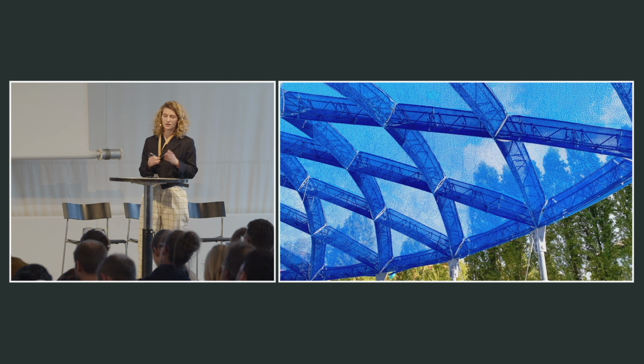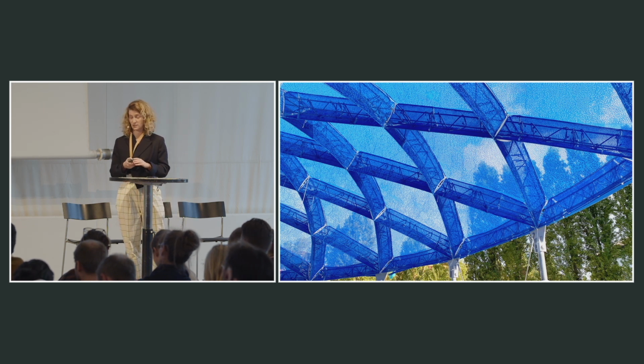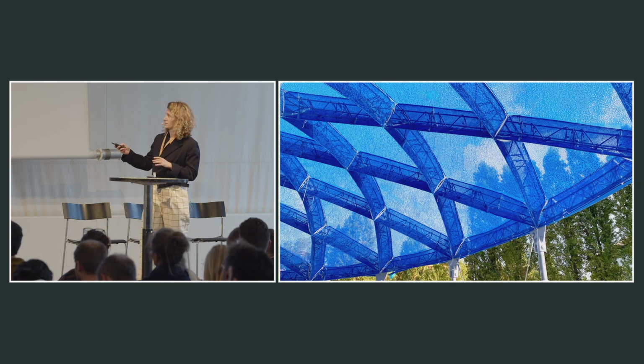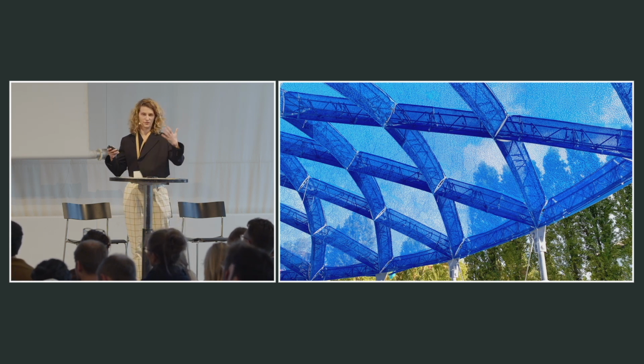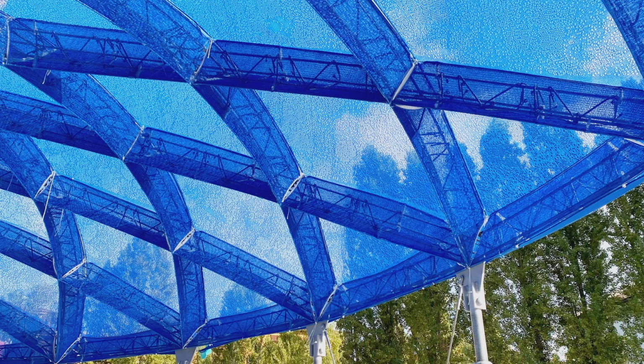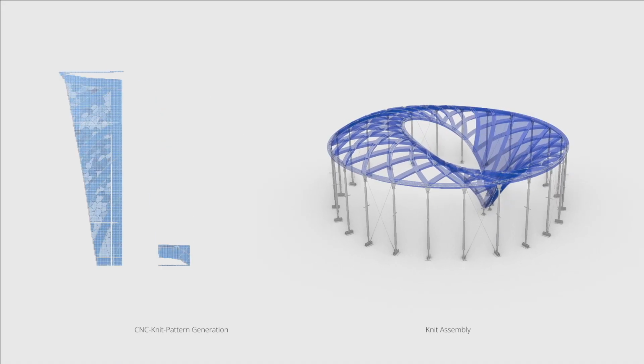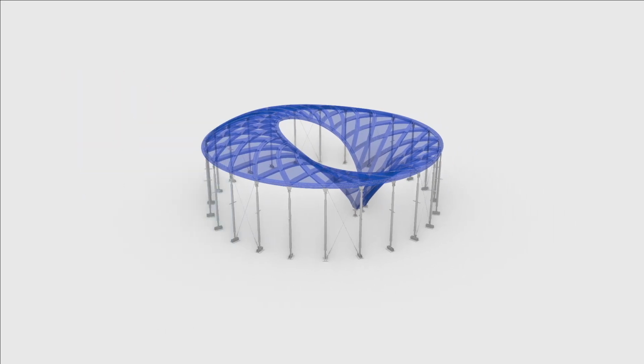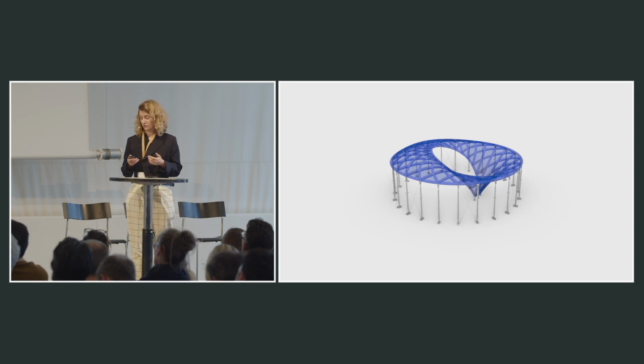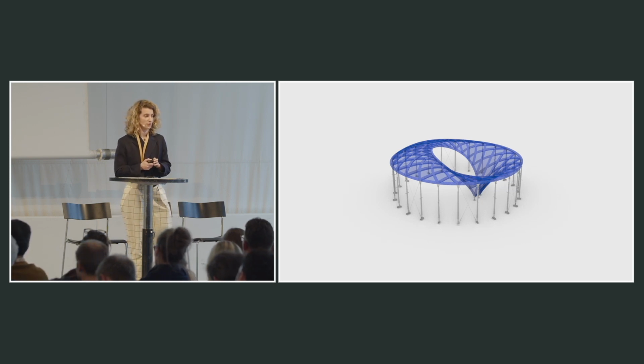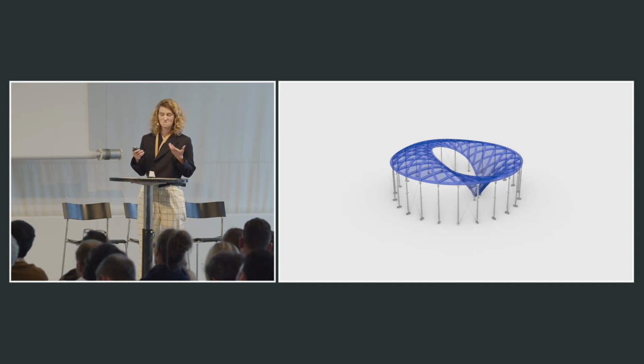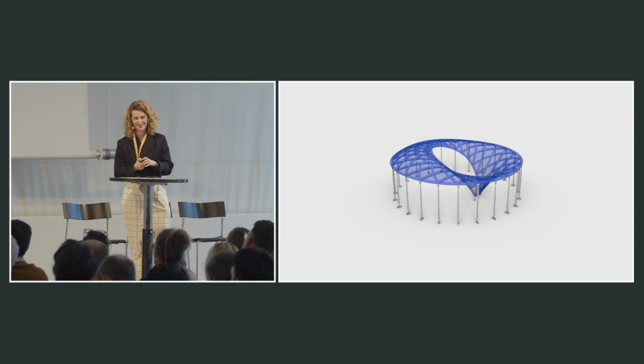So what you'll see here is actually a more or less zoomed in or detailed picture of the textile as it was assembled. And what you might notice, besides the X-ray through the structure type of view where we can see the rebar cage, you'll see that the diagrids in between, which were not meant to be structural or cast in concrete, have a very specific texture with different densities that can be manipulated and controlled during production. Now, to do this, we segmented the geometry in 74 parts. This was for production purposes, but also for being able to generate the production files accordingly, because it entails some computational weight in case the pieces are too big.